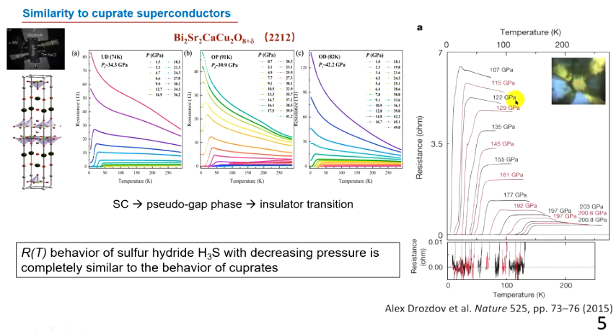And this behavior is very similar to the behavior of H3S, which was published and demonstrated by Alex Drozdov in the first publication about sulfur hydride in Nature in 2015. We see that at high pressure, around 190 to 200 GPa, most part of the normal state resistance behaves as in normal metals, as the Fermi-liquid theory predicts. But when we decrease the pressure, we see that the temperature coefficient of resistance changes its sign. And now at 107 GPa, we see that resistance decreases when the temperature increases. So it's opposite behavior than it should be in Fermi-liquid metals. So it's definitely H3S. It means in H3S we cannot use Fermi-liquid theory. We cannot explain the behavior in normal states of this compound using this Fermi-liquid theory. Definitely pseudo-gap phase, definitely strange metal.